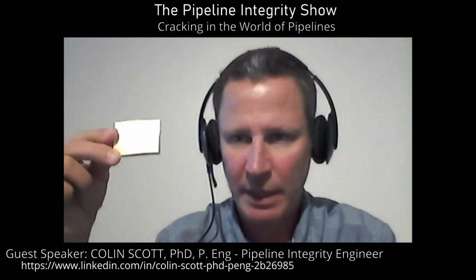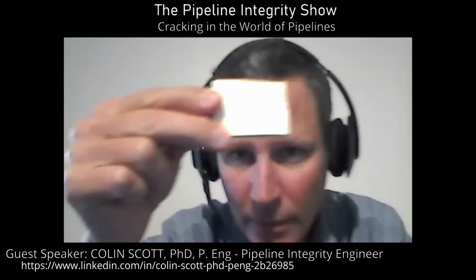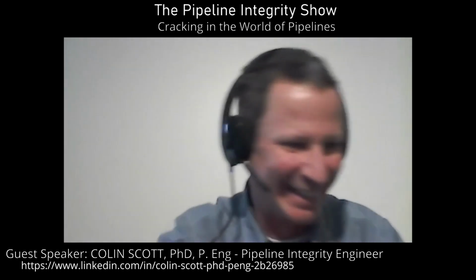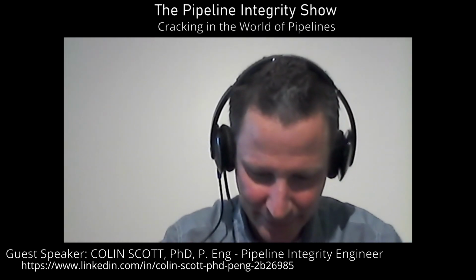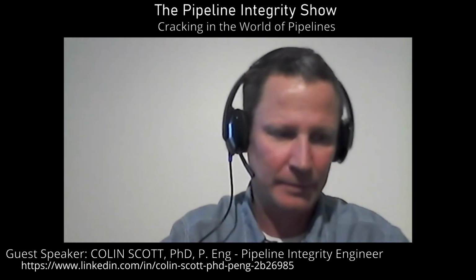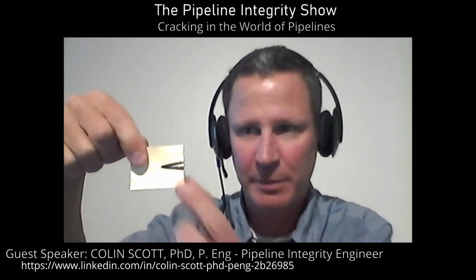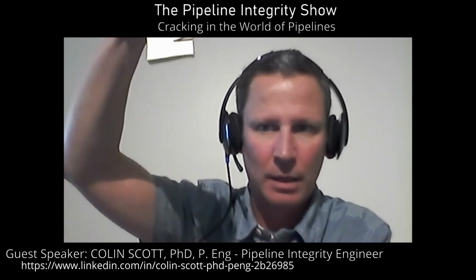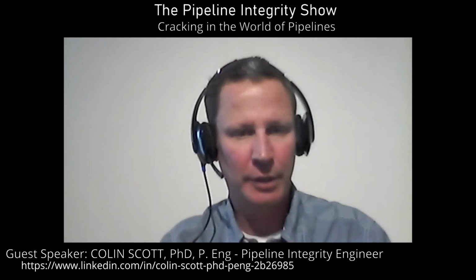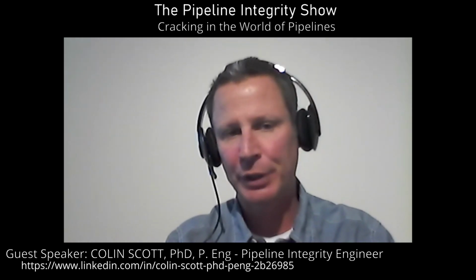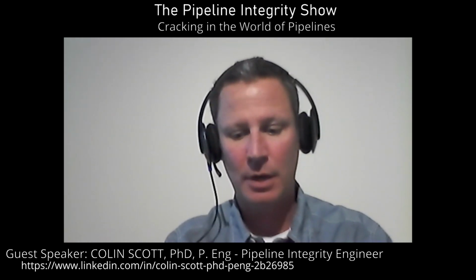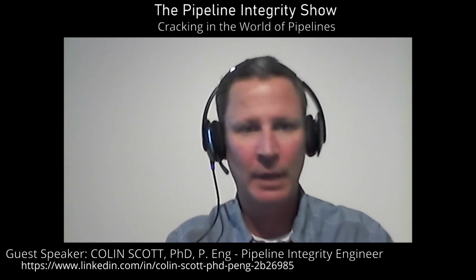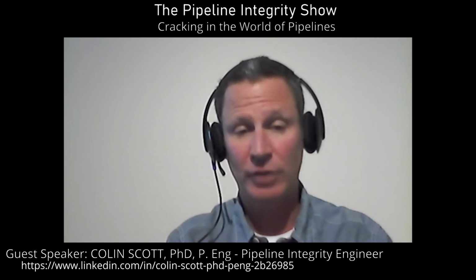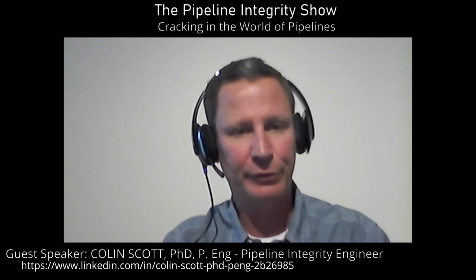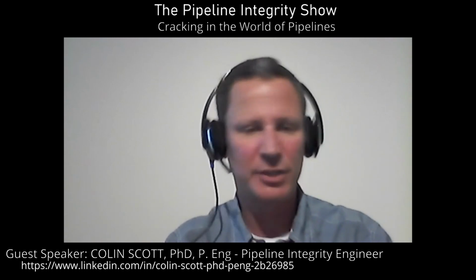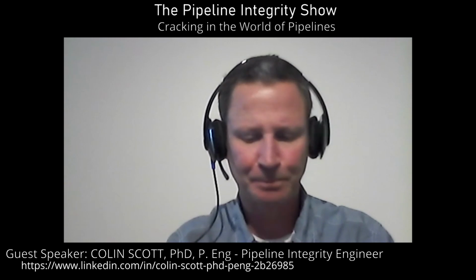I take my little compact tension specimen and I just pull on it. And at the point at which the fracture occurs, you can back calculate the critical stress intensity factor that caused that failure. And the stress intensity is based on the stress applied and the square root of the crack depth. And then there are some correction factors for geometry.